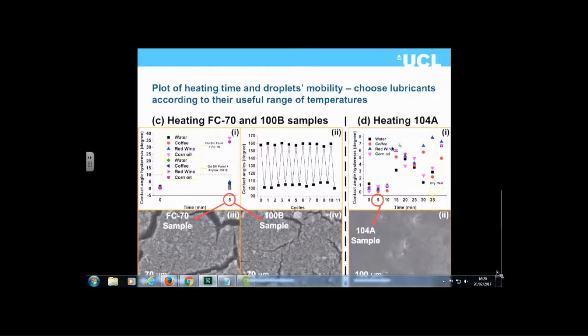Here, this is an illustration of the contact angle hysteresis associated with our particular coatings. For both water, coffee, red wine and oil, they were very resistant to both of those materials, and we could remove the lubricant layer and then re-add it and it would still function.